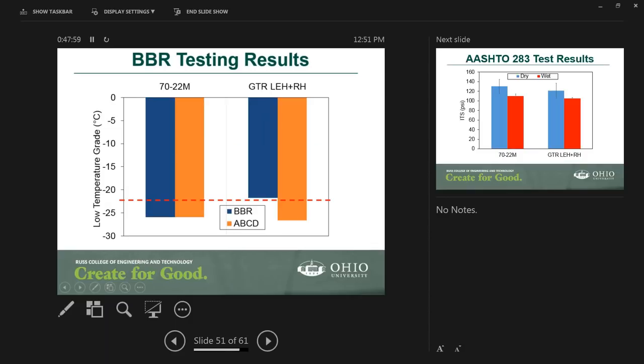Now for the low temperature, the GTR actually barely, I would say, failed the minus 22. In this case, it was 21.5. Some samples of the binder actually met in the BBR. Now, when we did the ABCD testing, it actually met the criteria, and it was almost a minus 26 or higher.